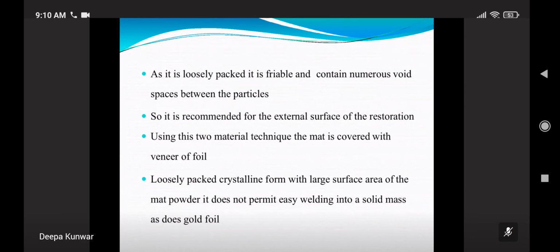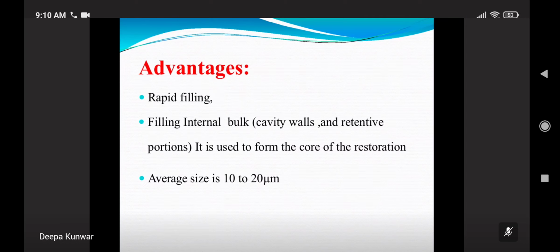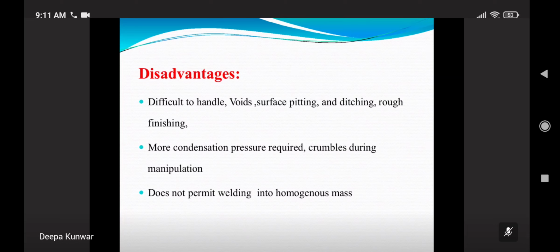Okay, loosely packed crystalline form with a large surface area of the mat powder doesn't permit easy welding into a solid material, as gold foil does. Advantage is rapid filling of internal bulk. It is used to form the core of the restoration, and particle size is 10 to 20 micrometer. Disadvantage: difficult to handle, voids, as already noted, surface pitting and ditching,